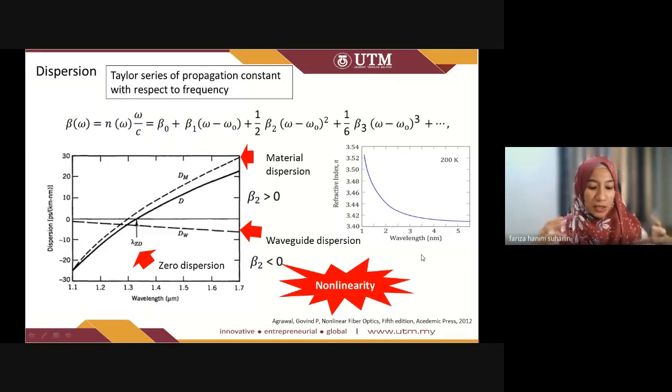But when we start moving on to the nonlinear responses, it is very important to bear in mind that this linear response plays a role in supporting the nonlinear response, because if we have high loss, high attenuation, you do not have enough power to get the nonlinear effect. If you can balance, or you can work in the anomalous dispersion regime, you can observe many interesting nonlinear phenomena inside the optical fiber. So all of these interactions are very integrated with each other.